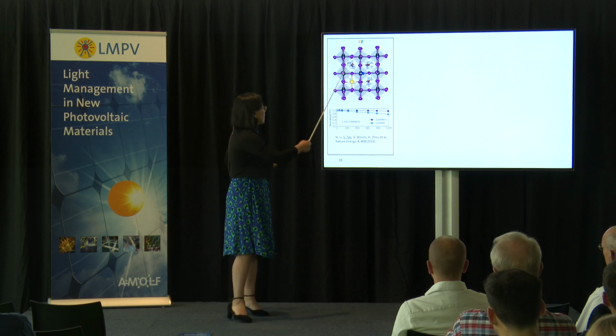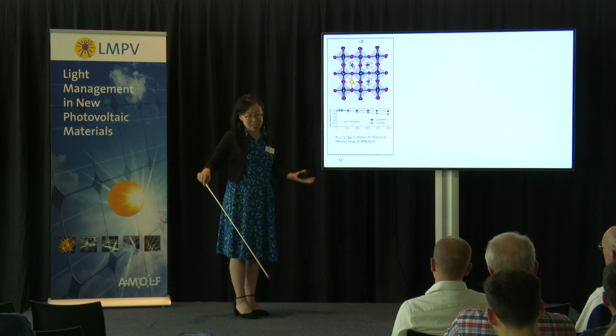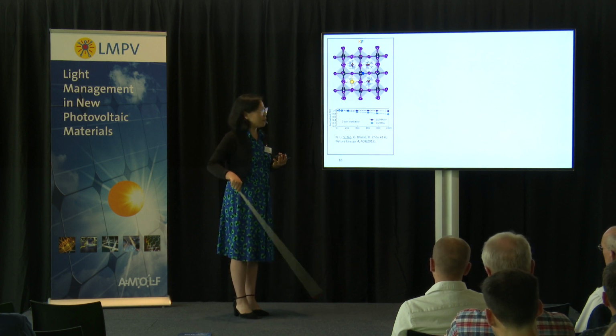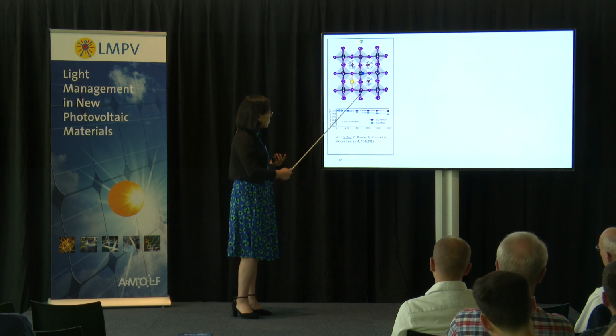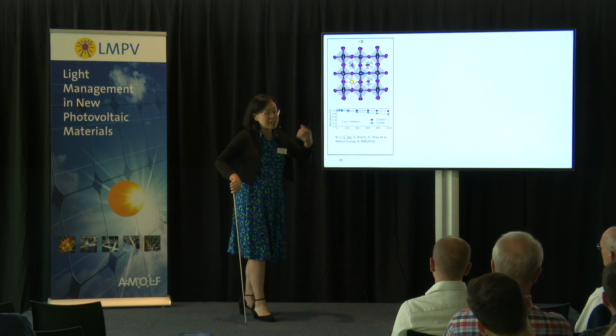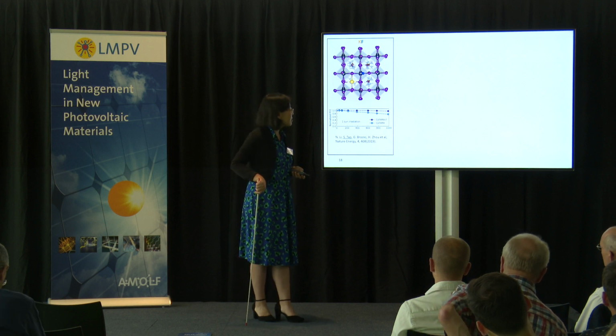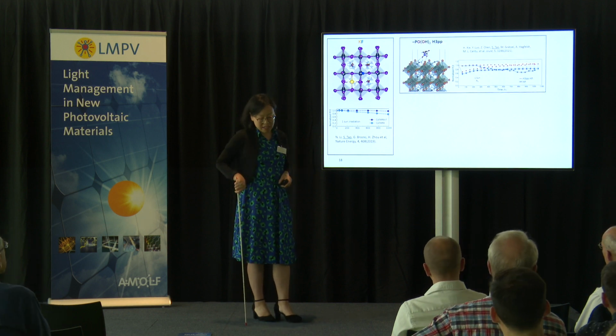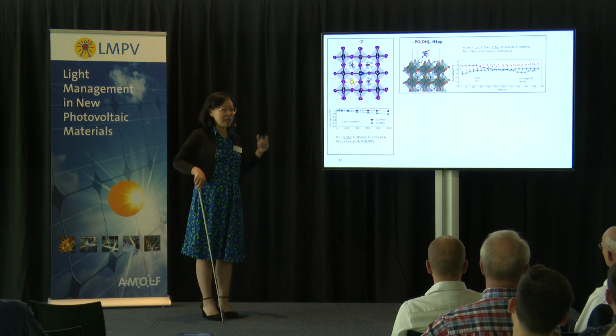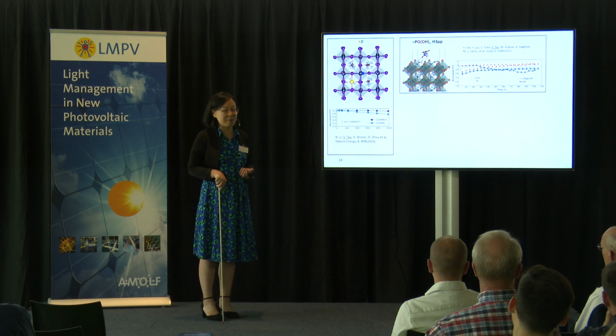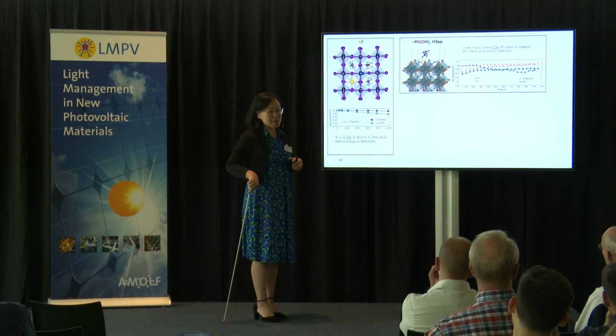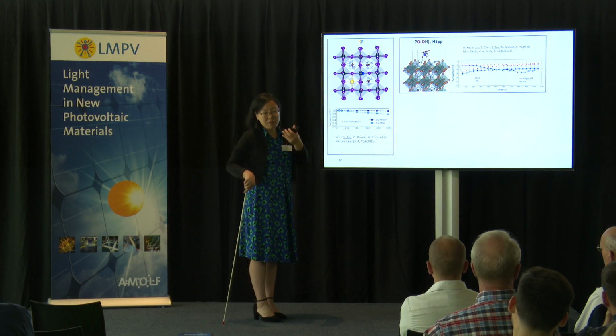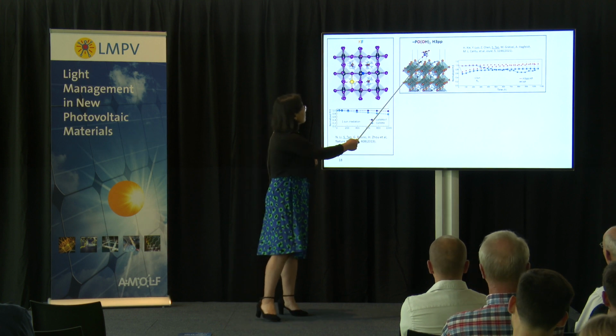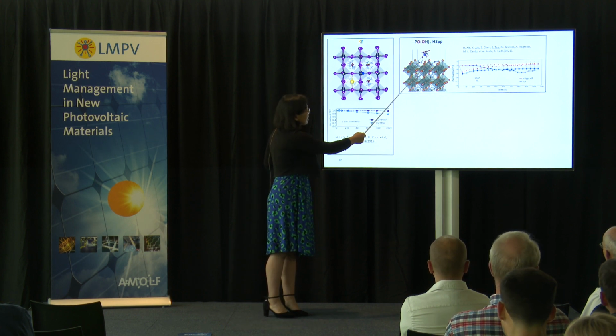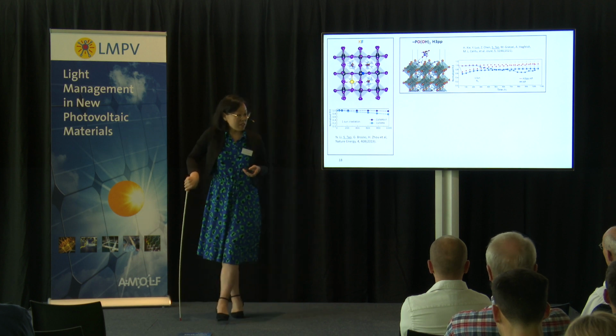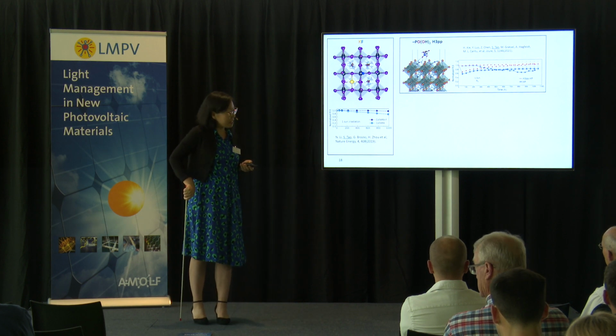Once it goes on the surface, it forms a strong bond with everything on the surface, forming passivation of every species up here. As a consequence, we actually get slightly more stability in the solar cells. Okay, the next example contains oxygen species, this time a big molecular cation. Again, this does not go to the bulk because it's too big, it comes to the surface. They form different bonds, this time oxygen-lead and also oxygen-hydrogen bonds. It gives a similar increase in the stability.